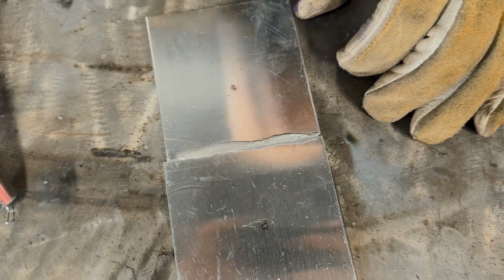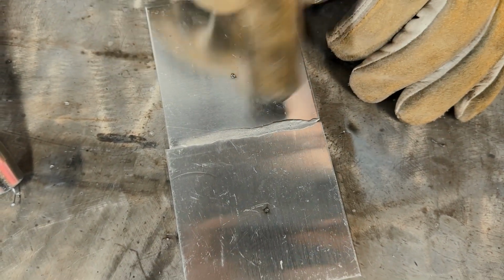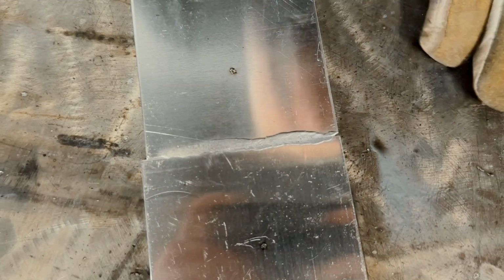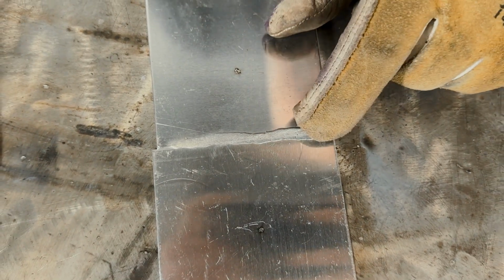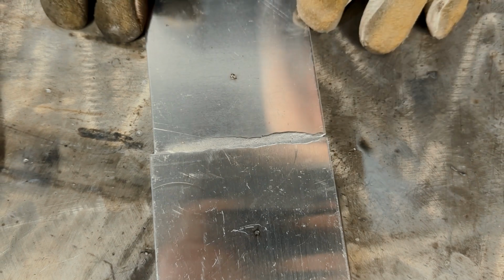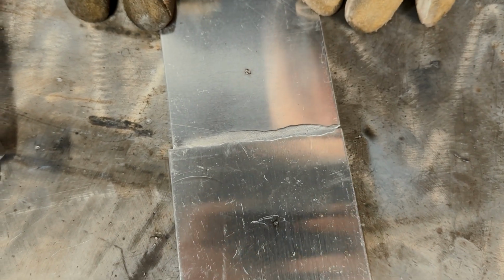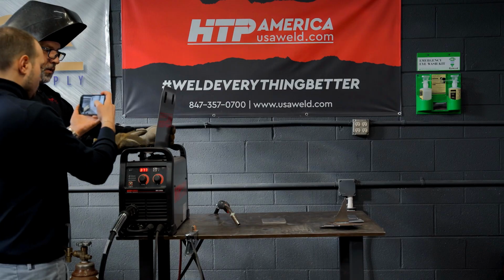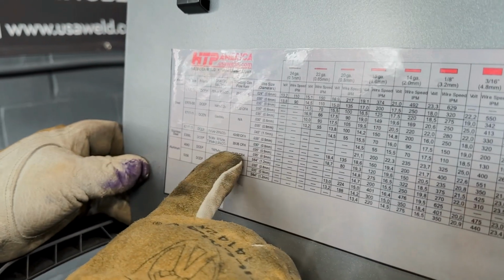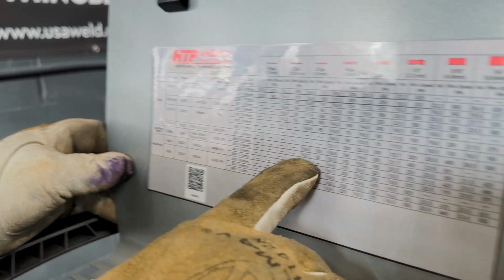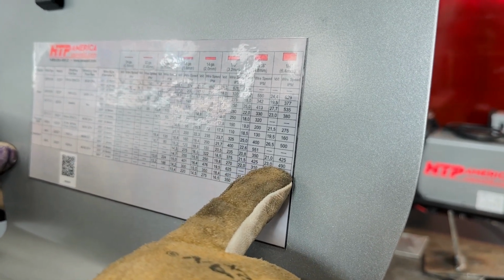But now the truth comes looking at the back side. Full penetration weld, no cracks in it. And the table as a heatsink did its job with slightly too high settings. It kept all the material contained. So now the next step is using the same wire, 4043-035, all the way up to 1/4 inch, 490 inches per minute at 23 volts.